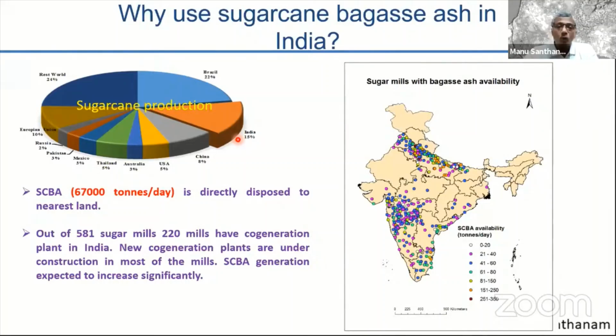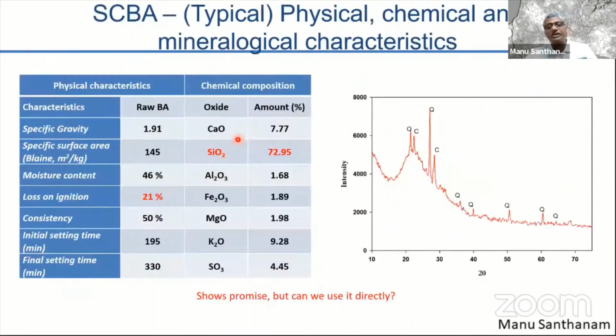So you have local availability of this material, and in many instances it works out quite favorable to the use of fly ash for the production of blended cement. But then we need to be convinced about its properties. So we actually undertook a large research investigation and looked at physical, chemical, and mineralogical characteristics. As you can see, it does have a very high amount of silica. And if you look at the X-ray diffraction pattern, a lot of the silica seems to be in the amorphous state, which indicates that it could possess a good reactivity.